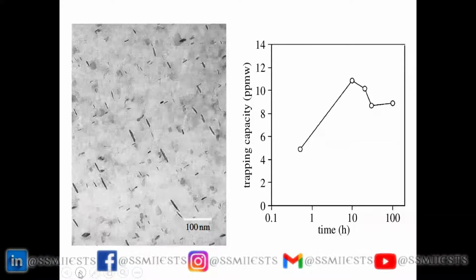But what happens is that when you get a crack, there's a stress field around the crack, and the hydrogen migrates towards that, so its effective concentration is greatly increased in the region which is subjected to the worst circumstances, and therefore you get embrittlement. So if you introduce hydrogen traps inside your material, then you stop it from diffusing and you improve the properties. And the graph shows you that, with appropriate heat treatment, we can trap something like 10 parts per million of hydrogen at these traps. So if you go to the next slide,